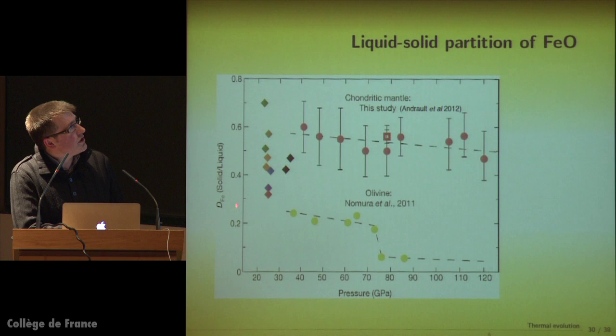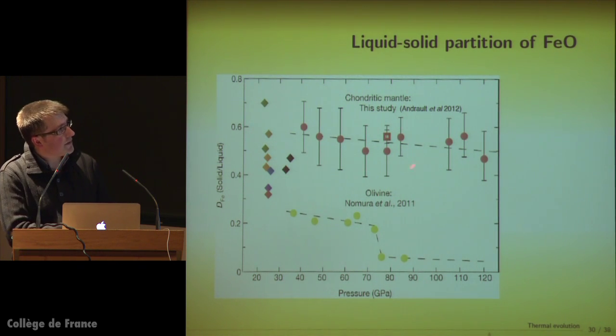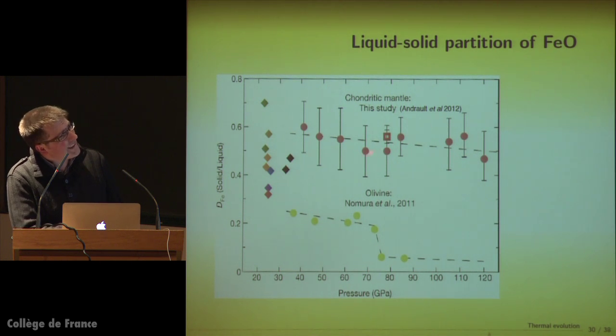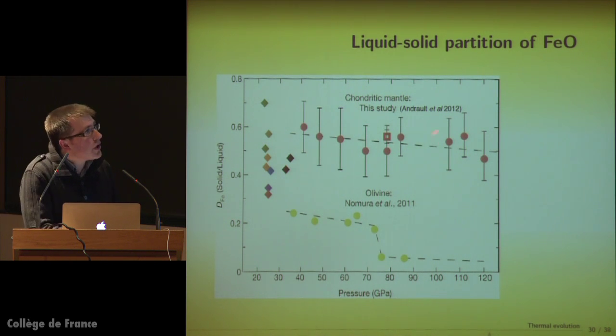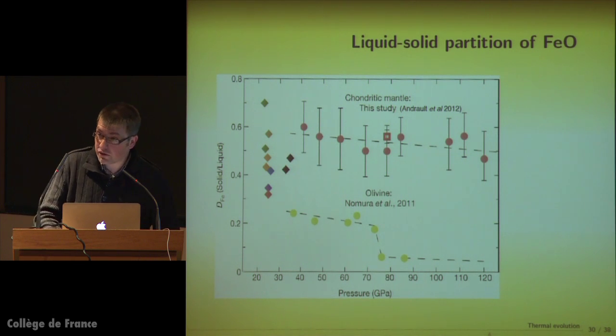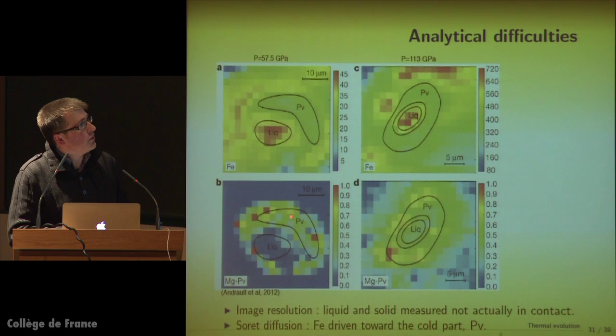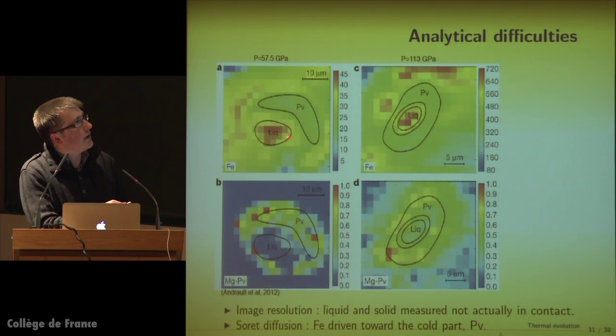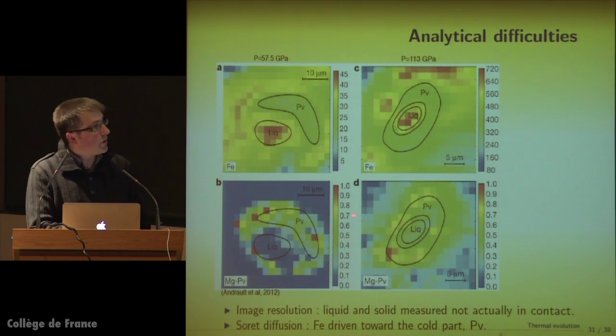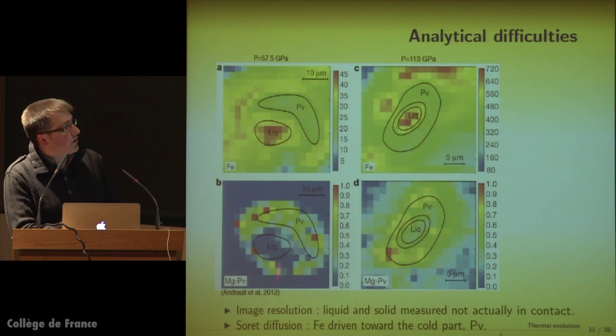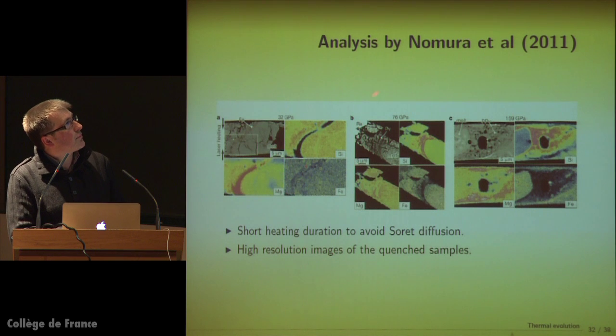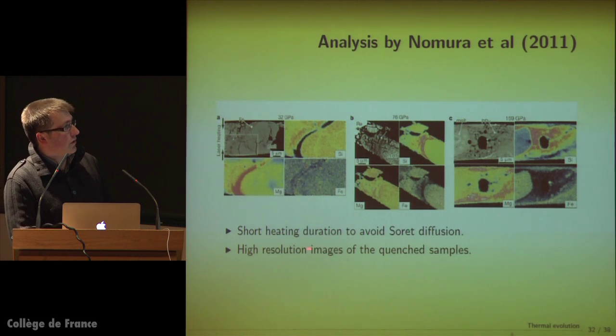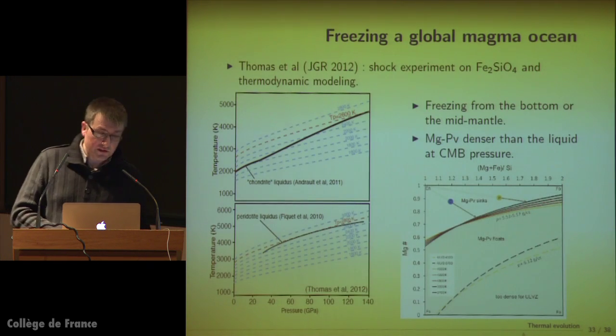This is the study by Denis Andrault, and I'm sure I'm going to talk about that later. They find that iron indeed partitions preferentially in the liquid, but not much more, compared to this paper where they find a much larger partitioning of iron in the liquid. I want to mention that the way it is done is by computing the composition in this kind of area here, and the resolution is not great, so there might be an issue here. Also, the temperature gradients are very big, so there might be Soret diffusion. In the experiment by Nomura and others, they do very short heating to avoid Soret diffusion, and the images have much higher resolution, so that might be something to discuss.